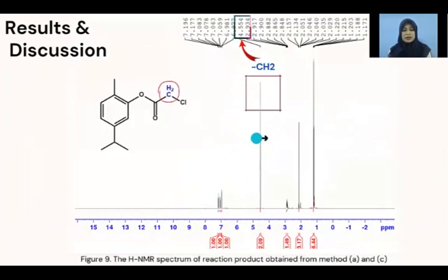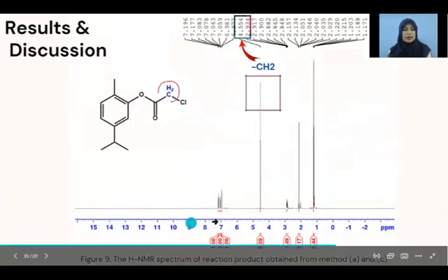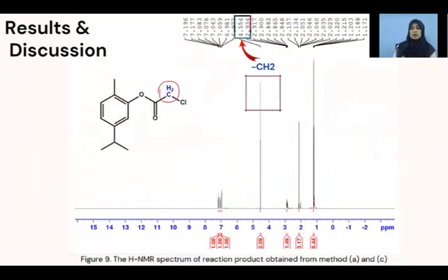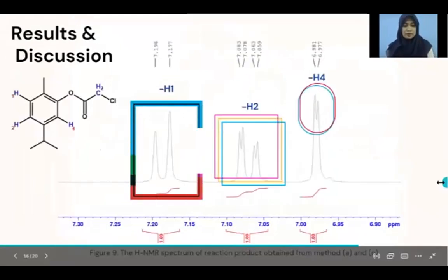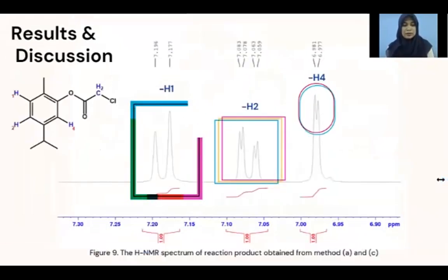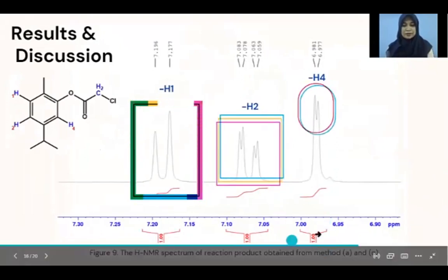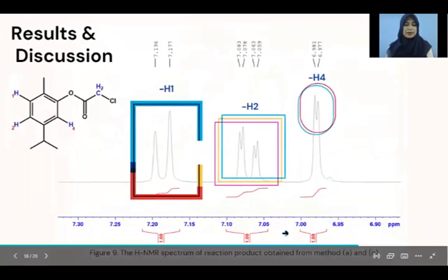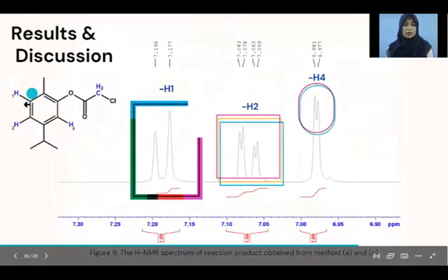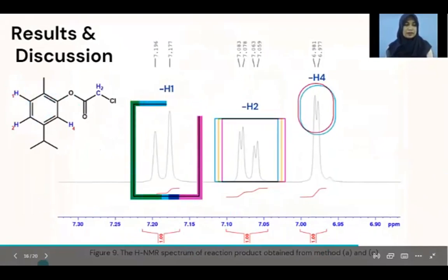The singlet signal at 4.554 ppm of the methylene protons is the typical signal of carvacryl ester. The typical singlet signal of carvacrol for the OH proton also doesn't appear. The three signals at the chemical shift around 7 ppm represent the aromatic protons in carvacryl ester.